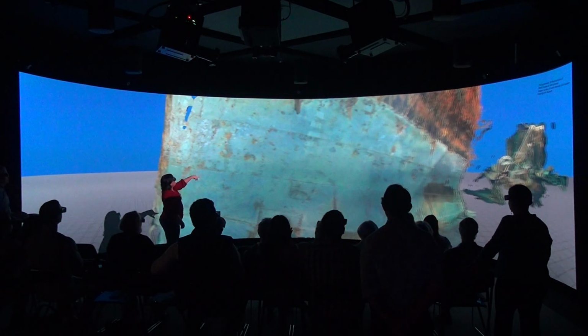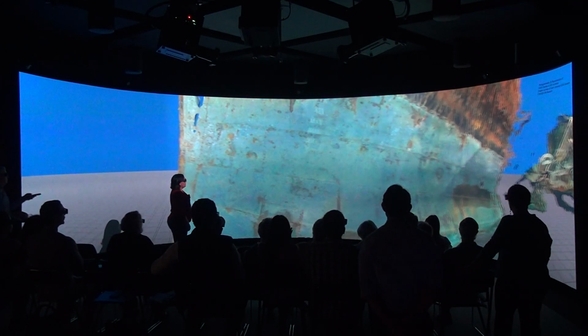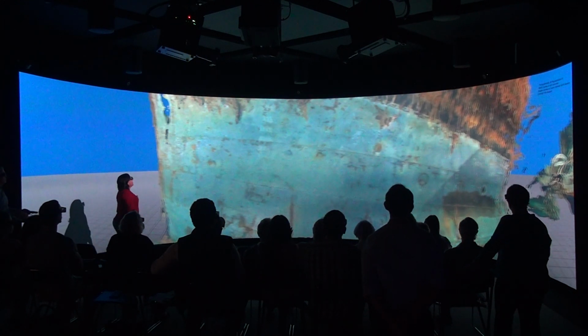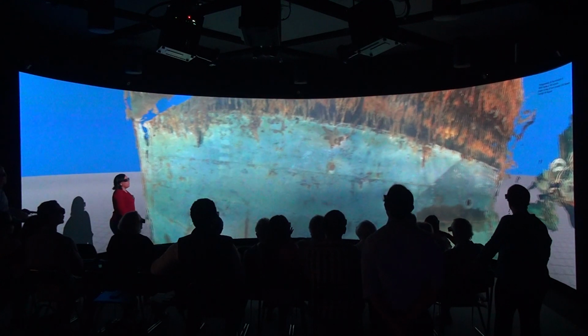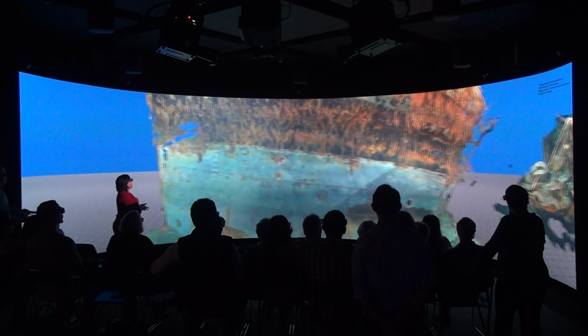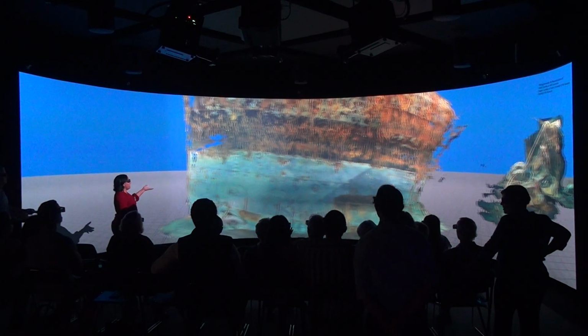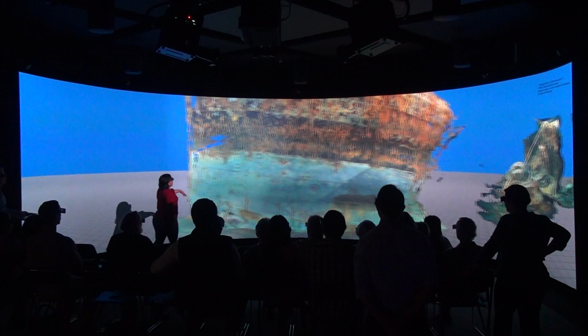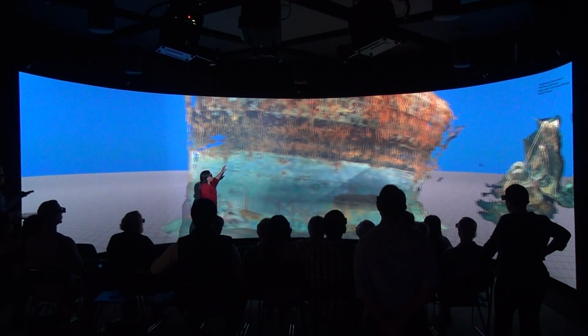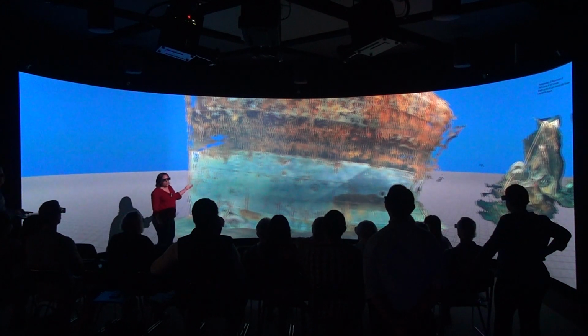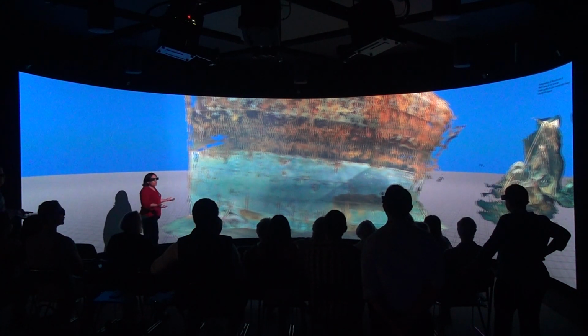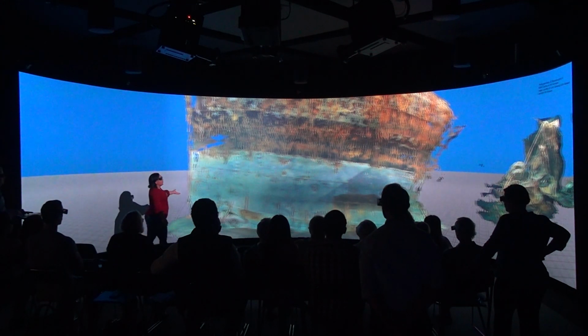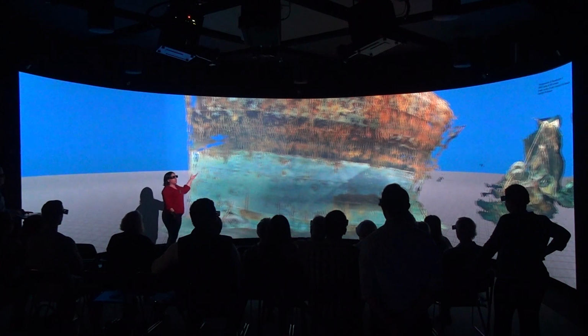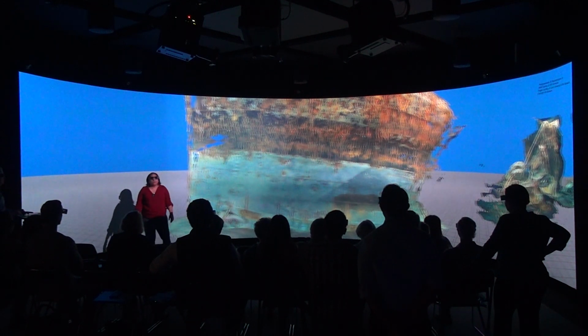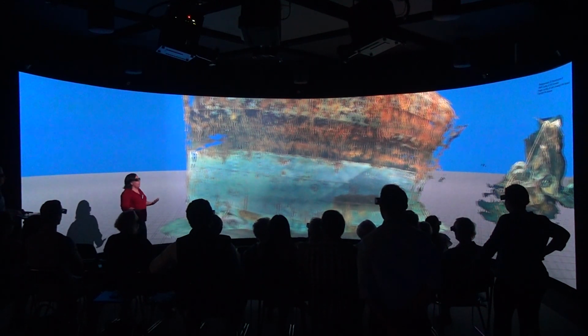You can see the depth measurements, or the waterline measurements, here on the hull. So if we can zoom out a little bit, what do you notice here? The ship is upside down. So this is the above water portion of the ship, and that is the underwater portion of the hull. You can see that the underwater portion of the hull is a preferential rusticle site. So we were wondering, why is it happening? Why has this above water portion of the hull, over the same amount of time, no rusticles, or at least not as abundant as the underwater portion of the hull? And this happens in both shipwrecks.